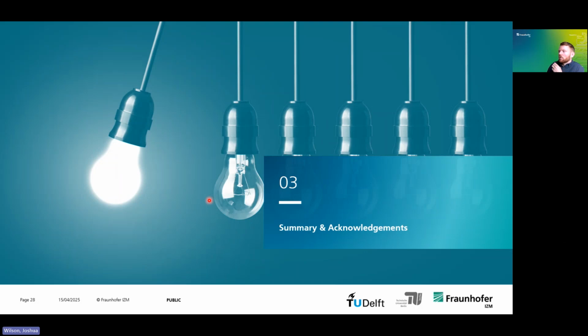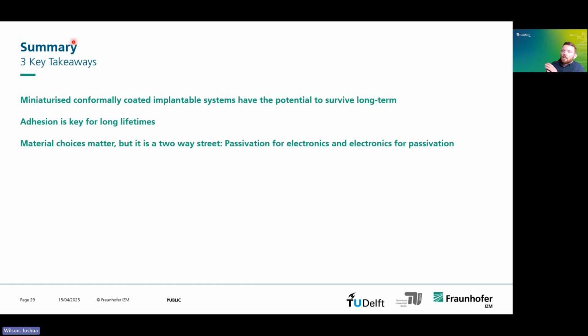Okay, and just to summarize, I'll give you some key points. Firstly, miniaturized conformally coated implantable systems have the potential to survive long term. So this is one key takeaway, but really the biggest takeaway would be the second one. Adhesion is the key for long lifetimes. You really need these things to stick together, because if they don't stick, then you start to have voids where the body fluid can get in, begin the corrosion process, or you can have delamination, which leads to rapid failure of the device. And finally, the material choices really matter.